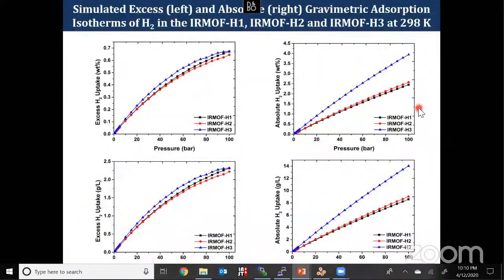And this is for 298 Kelvin, and that is for 77 Kelvin. So here at 298 Kelvin, none of the MOF materials attain the saturation point, and the adsorption curve is still a straight line. So a lot of space, we still have a lot of room to store hydrogen molecules, but near room temperature, the material is not adsorbing more molecules.